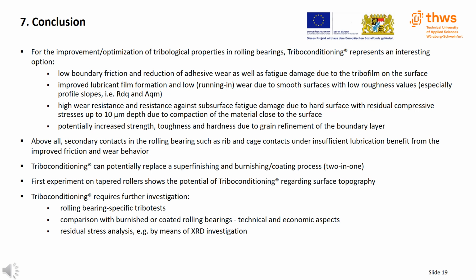This is due to the tribofilm. The smooth surfaces with low profile slopes R delta Q and AQM provide improved lubricant film formation and low running-in wear. High wear resistance and resistance against subsurface fatigue damage are achieved by the hard surface with residual compressive stresses down to 10 microns depth. Lastly, potential grain refinement of the boundary layer would result in increased strength, toughness and hardness.